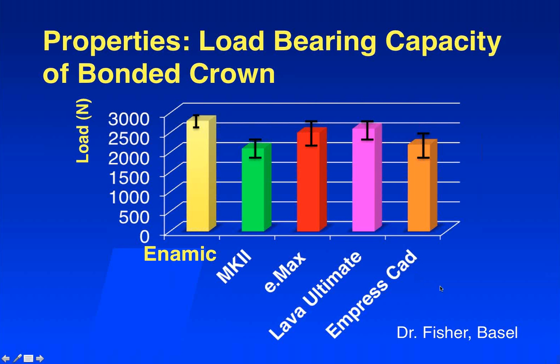Load-bearing capacity, and this is a very interesting study. We have our own studies that corroborate Dr. Fisher's work. And in this case, you're taking restorations, milling them out to 1.5 millimeters thickness occlusally and 1 millimeter thickness radially, bonding them to an underlying substrate that's like dentin, and then doing the load-bearing capacity.